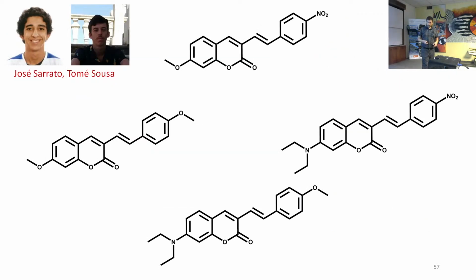So we are currently synthesizing these compounds. In this special case, the electron goes from this nitrogen to this group in here. It produces an extremely large change of dipole moment, and that's why it has a very large Stokes shift, and it pushes the emission to the near infrared region. This part here is quite flexible, which means that in solution, these molecules have low quantum yields. However, we are working in extremely viscous materials, so that shouldn't be a problem.